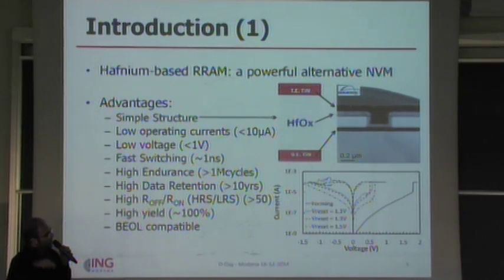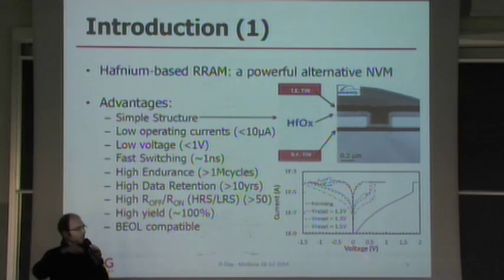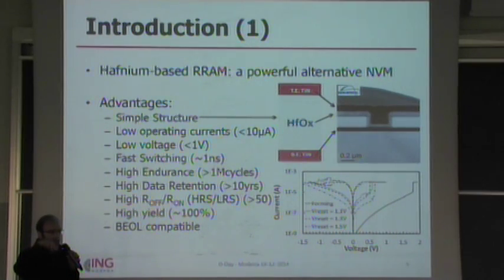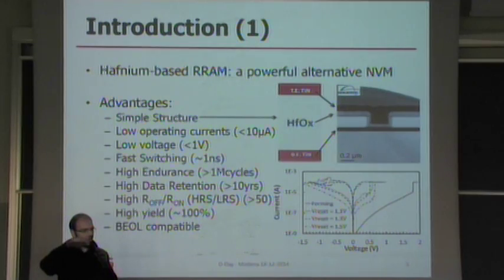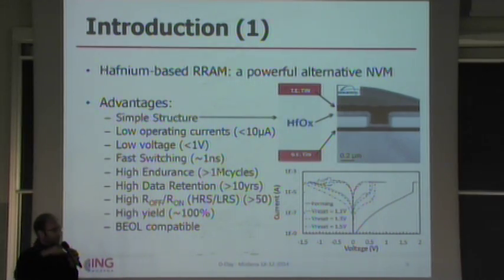So first of all, with this kind of forming, a so-called electroforming procedure, we can break the device down, we can create a conductive filament, and we determine a low resistive state. However, when I reverse the polarity across the device, I can actually switch this device back to a higher resistive state. Actually, we just locally break the filament, and I can do this on and on, and I can switch the device back and forth from low resistive state to high resistive state and vice versa. So here we have a memory, and we actually have a pretty good memory.